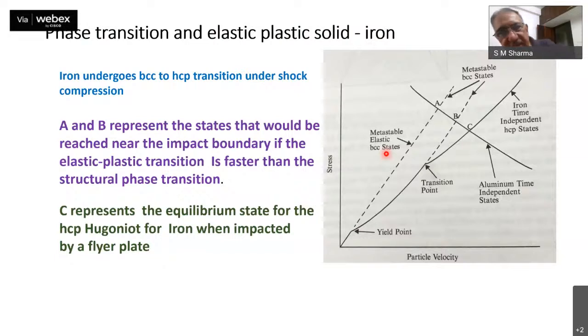Now, a still more complicated situation could be that a material has a phase transition in addition to the elastic-plastic transition. This is an example of iron. In the very first lecture we talked about iron, where the phase transition was detected with the help of shock compression. So in a case like this, you see that this is the first metastable curve of the iron representing its initial BCC phase.